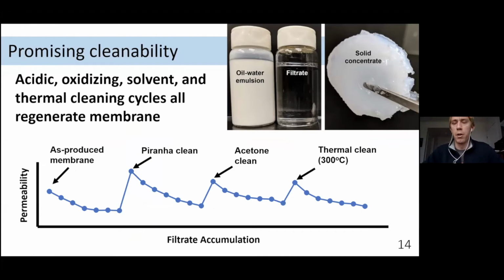We basically sucked all the water out of this solution to leave the solid concentrate, which you can again see on the very far right side. Then we've done this in cycles where we performed the experiment, cleaned the membrane, put it back in, duplicated the experiment once again, and then performed a different cleaning step. We can see that through different cleanings, be it with piranha solution, which is concentrated sulfuric acid and hydrogen peroxide, or organic solvents, or thermal cleaning, we can rejuvenate the flux and permeability of that membrane back to the initial value.